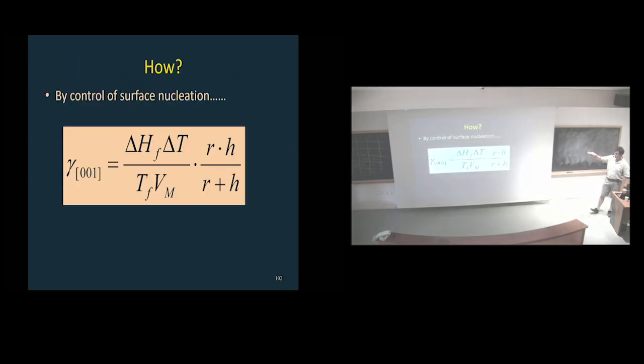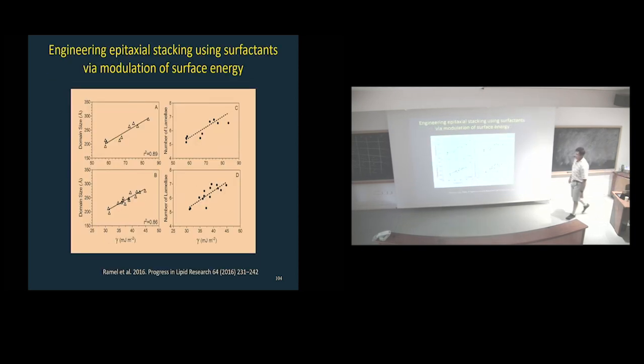We also managed to work a little bit with surface nucleation on the surfaces that I talked to you about, and we can actually change the thickness of the platelets from 5, 6, and 7 lamella based on shear. But this shear is in a scraped surface heat exchanger, at infinite cooling rates, the ammonia valve was open, and it was as fast as the machine could go. We're talking about a soft blade ripping a surface that is at minus 20 degrees, going at, I think, about 300 RPMs on this gigantic machine. I don't even know what the shear is in there. It's absurd on an extremely thin layer. And with that, we could change the thickness of it. So it requires a lot of shear.